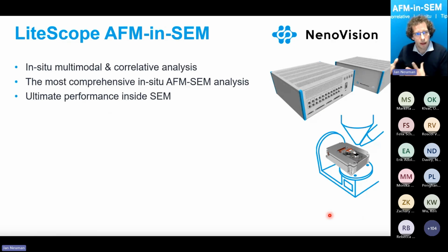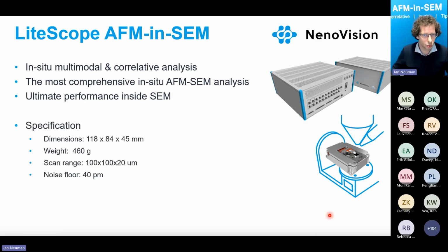Actually, it's also compatible with Thermo Fisher TEMs. And the last part is our LiteScope, AFM inside the SEM, specifically developed for in situ multimodal correlative analysis, which enables you to really make ultimate performance measurements inside the SEM. Here I would like to highlight some specifications. The area which we are able to measure is roughly 100 by 100 microns, with a 40 picometer noise floor in the Z range.